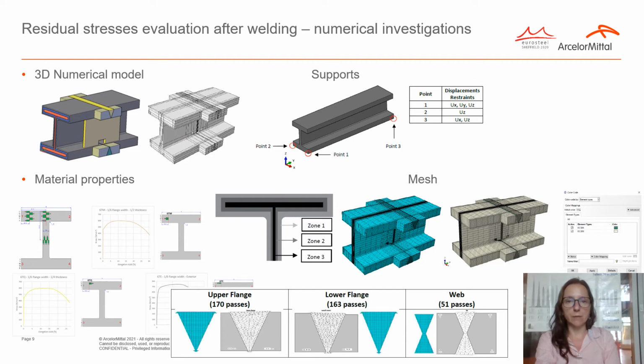The material in the numerical model was defined according to input data from tensile tests together with mechanical specifications and temperature variation properties. The temperature variation properties were based on the European standard Eurocode 3 Part 1-2, and the kinematic hardening stabilization option was used for the plastic input in Abaqus. In order to consider the cyclic loading induced by the welding process, heat and cool down causing expansion and contraction of the material, and to correctly define the mechanical properties of the model, 3 different material zones with different properties were defined.